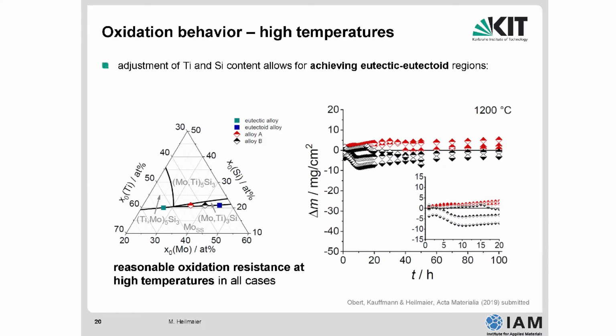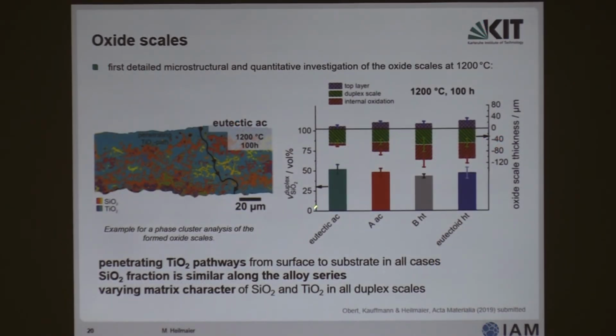But you can imagine a turbine has to be ramped up and cooled down. So you have to go through the 800 degrees centigrade region sooner or later with your alloy. So it doesn't help you having an alloy being oxidation resistant at 1200 C. At 800 it must show at least some oxidation resistance, because during start and landing the alloy will see this temperature. Okay, I skipped that for the sake of simplicity.